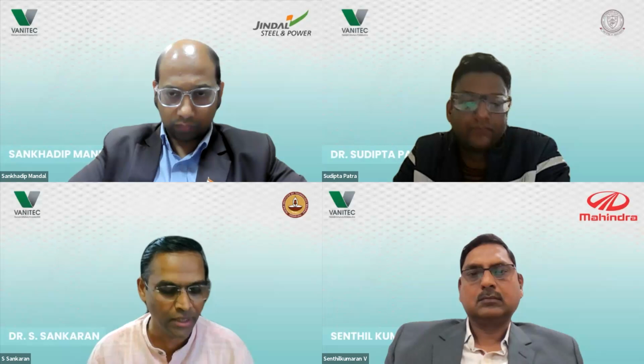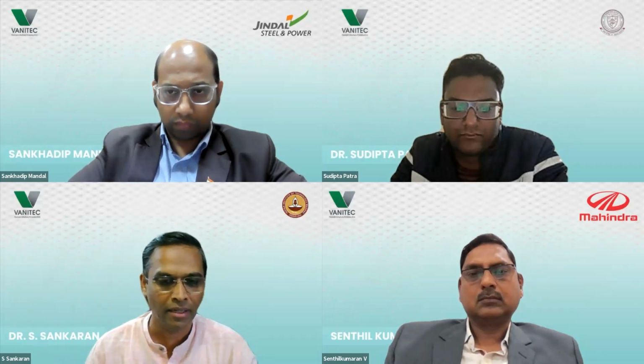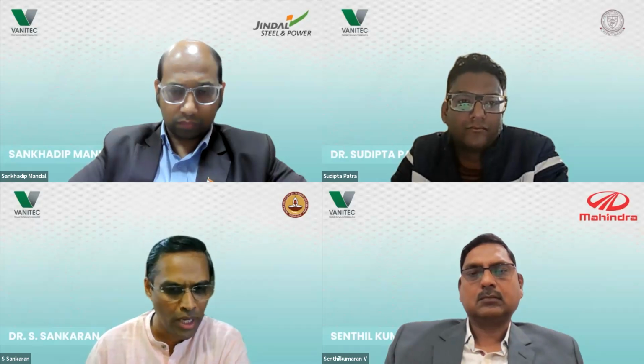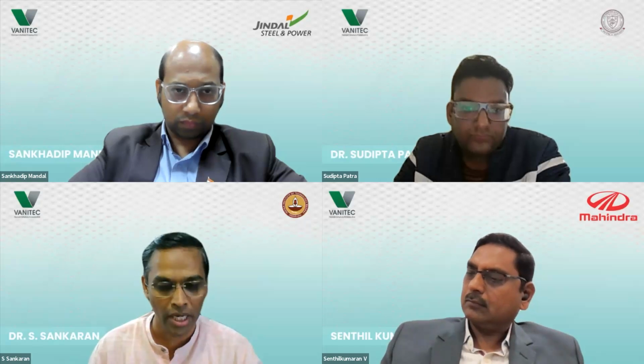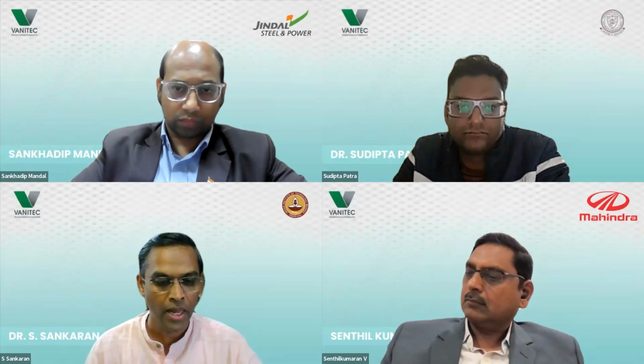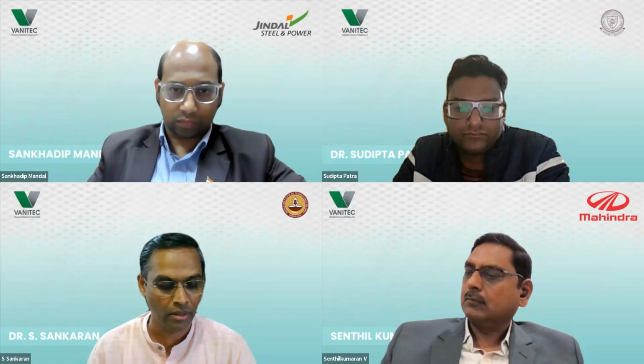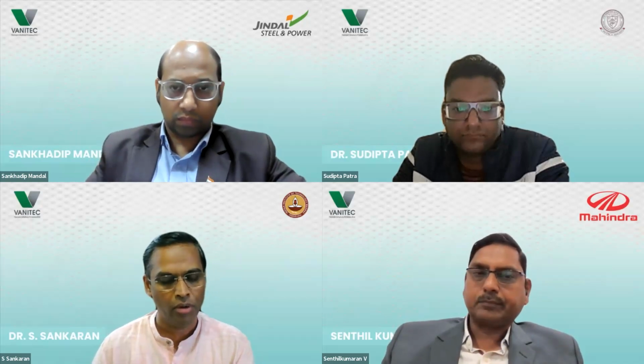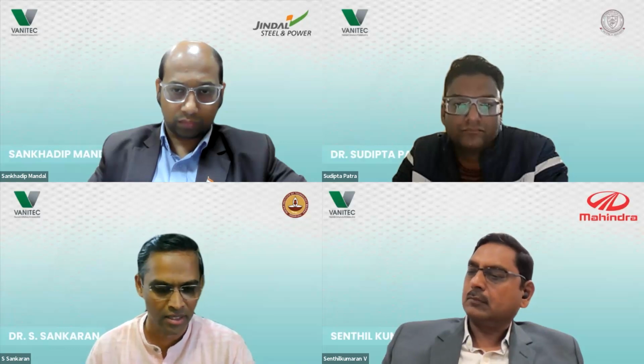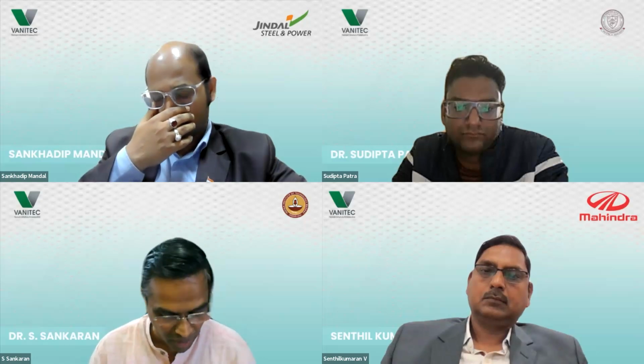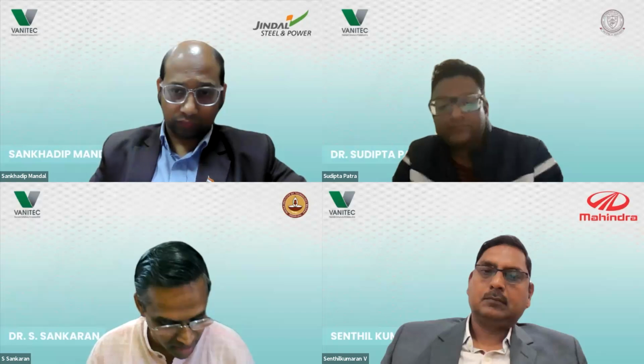Okay. So what I used to do is take all these precipitates extracted on the carbon extraction films, and then do individual EDS, and take the spectral ratios to find out the stoichiometry. It is a qualitative stoichiometry, but it gives an idea what kind of intermetallic it forms when you use more than one microalloy. People use them for different purposes, but characterizing them is a huge challenge. As I said, some of the precipitates are quite intriguing because they form a core-shell kind of precipitate, the core being a nitride and the shell being a carbide. So this is what my research found out. All of them were published a long time back. I can give you the reference if anybody is interested. So that was about that postdoctoral research.